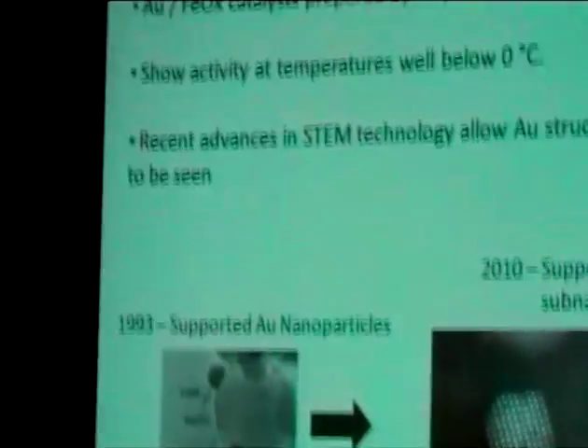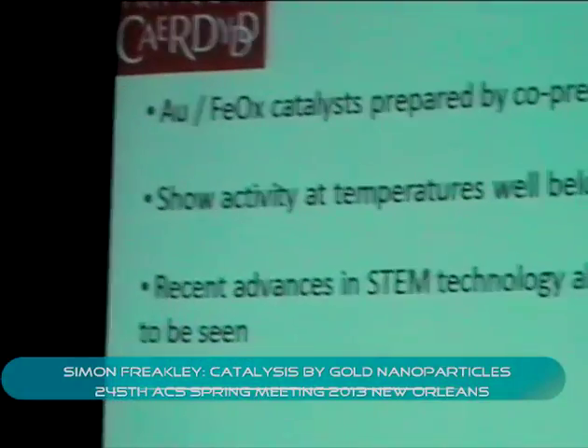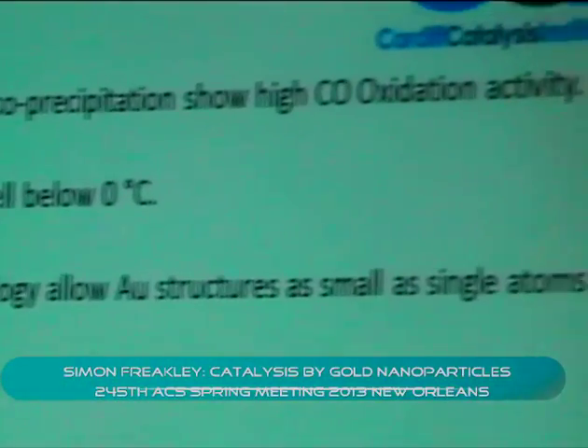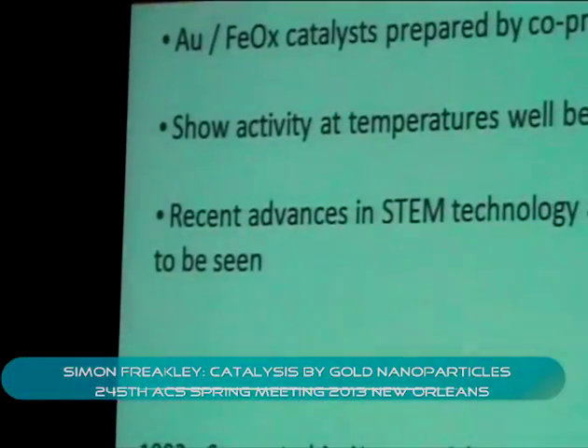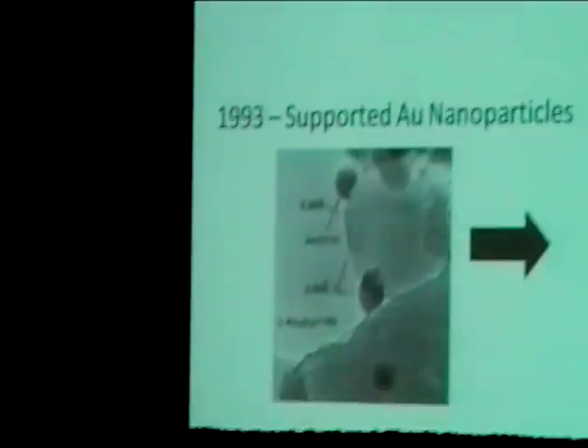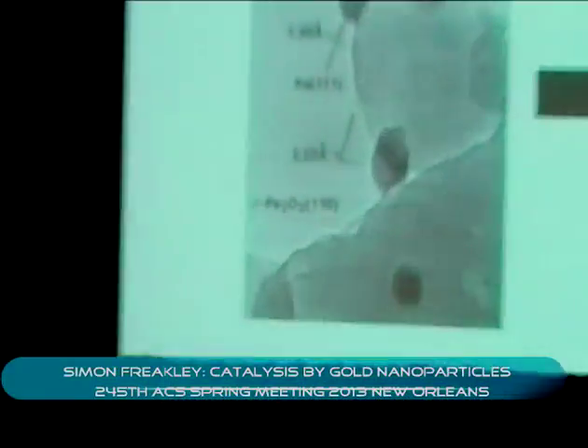So gold on iron oxide prepared by co-precipitation was one of the catalysts first shown by Professor Haruta to be active in this reaction. And when prepared by co-precipitation, these catalysts show exceptional activity for CO oxidation, even at temperatures well below 0 degrees C.